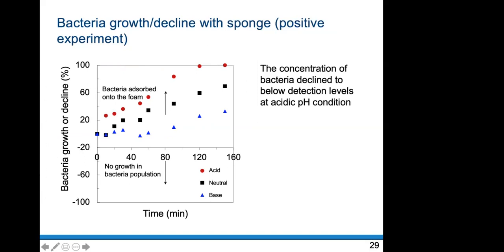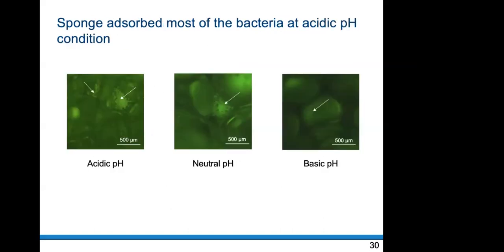Here, this specific experiment is run with the sponge, where in the LB I kept this stationary sponge so the bacteria can go and attach to the surface. As I said, at basic conditions these cells tend to repel from the sponge because of the same charges. So at basic and neutral conditions, we see very few cells attaching to the surface. But when it comes to acidic conditions, most of the bacteria are attached to the surface. It shows 100%, but it is actually below the detection level of the instrument I was using. So the bacteria is absent from the water, and it is going to the sponge surface.